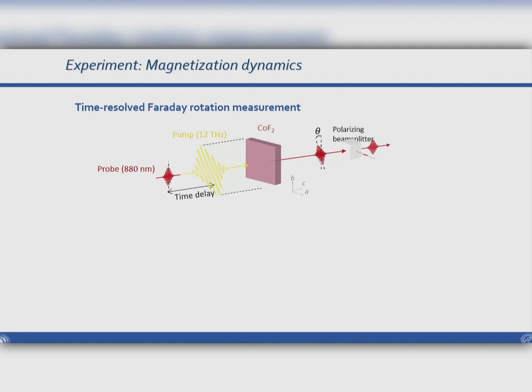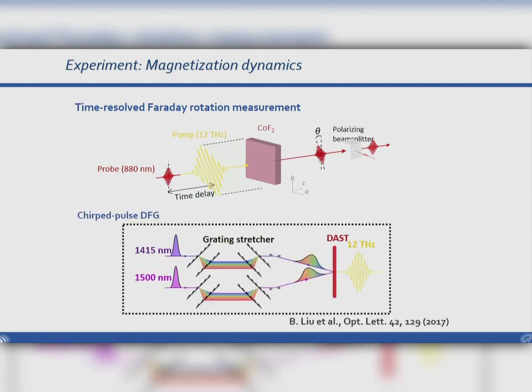So we did time-resolved Faraday rotation measurements. And because this cobalt fluoride involves relatively light atoms, the frequency of the optical mode that we have to drive is at 12 terahertz. To pump it, we had to develop a specific source that can produce very selectively narrowband pulses, which are, by the way, tunable between 4 or 5 and 20 terahertz. So now very easily we can tune this excitation across the whole terahertz frequency range. And using this particular type of mid-IR or terahertz source, we were then exciting the sample with a 45-degree angle between the a and the b axis.